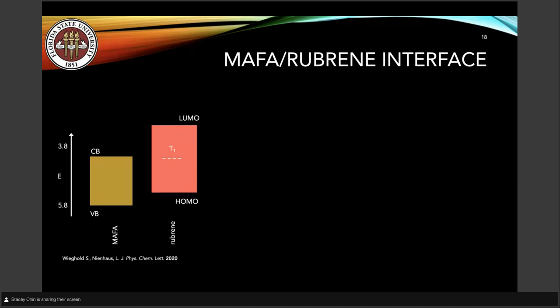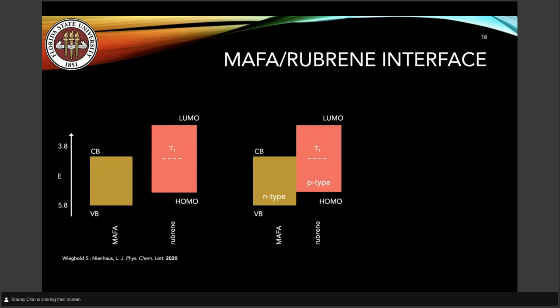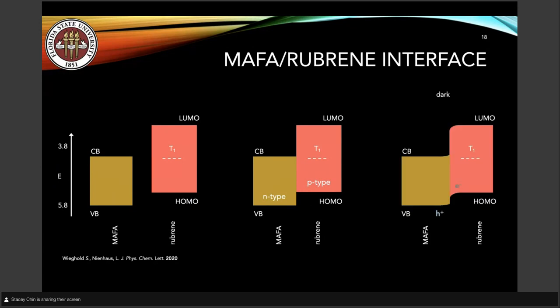So next, if you bring them into contact and consider the fact that this is an N-type perovskite and a P-type organic, of course they don't just stay the way they are, and you don't just have contact and the bands stay exactly the way they are. Rather, what happens is that, next, essentially, your charges move around a little bit to equilibrate and bring this system into a steady state. And so you have band bending and your electrons move from the rubrene to the perovskite, and you get hole transfer from the perovskite to the rubrene.